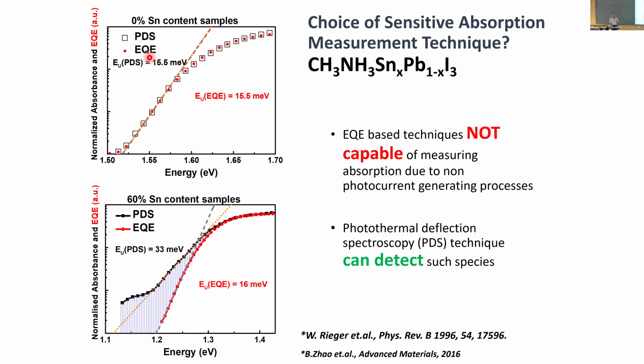So if you measure PDS, and you measure the photocurrent based technique, which I call EQE here, you see the same absorption, the same results, the Urbach energy is the same, not different. But if you go to samples where you have doping, what you will see is the photocurrent based method doesn't see it. So you end up measuring a different absorption curve, or a different profile, and the PDS measures something different, which is an additional absorption. So this shaded region is the absorption coming from the doped species absorbing light.